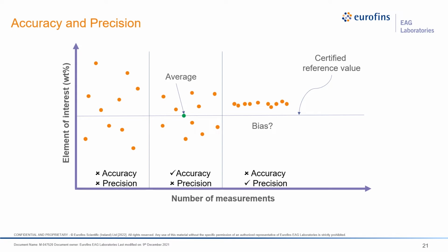The third case could be where measured values have very good repeatability, indicating that measurements are precise. However, since the measurements are not matching the certified value, the measurements are not accurate. This could be a case of a systematic bias, and by using an appropriate correction, we may be able to make the measurements accurate. The last behavior is like an eternal bliss, as one of my colleagues likes to say. The measurements are perfectly precise and accurate.